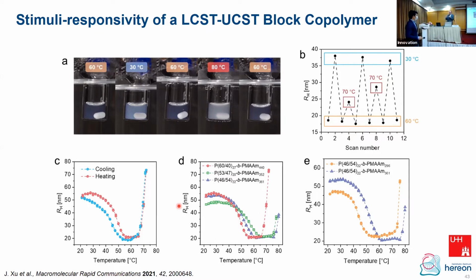Yeah, all this work is done with a photoinitiator. We started with thermally initiated RAFT, and there we had the problem with the LCST, because we have to heat to a high temperature, and then we were above the LCST. We had to add an organic solvent to make the LCST higher. But then the polymerization was not really green. It was greener than the original ones, but it wasn't really green. Now we are in the organic solvent-free state with these polymerizations.